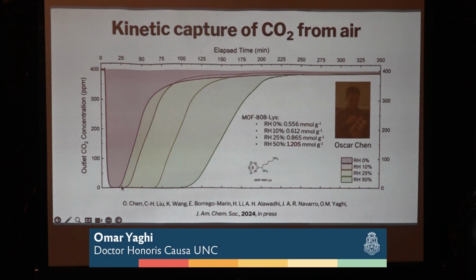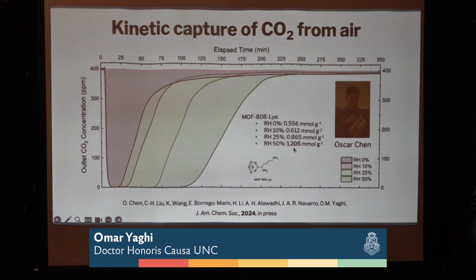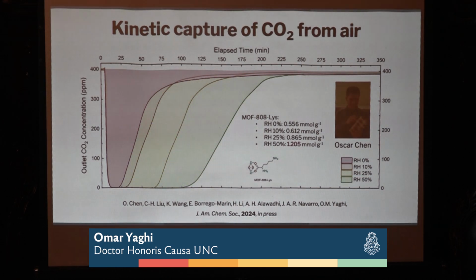That's what this says. And you've separated it from air, let's say right now in Cordoba, it's probably over 50% humidity, okay, with 1.2 millimole of CO2 per gram. Okay? For me to have a practical material, I need 1 millimole of CO2 per gram. So we actually beat the standard that is needed to commercialize this material.